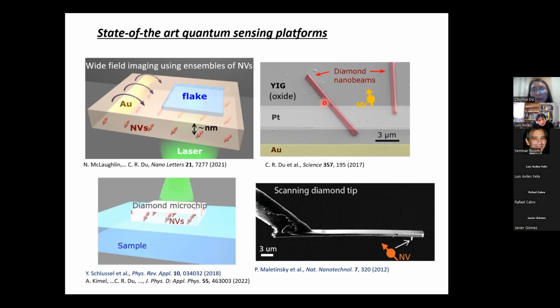So this includes patterning the diamond into diamond nanobeams with the width around micron size, or patterning the diamond into microstrips and transferring it on the material surface. So we can also use a fabricated diamond cantilever containing a single NV center at the end. Then we can attach this diamond cantilever to an atomic force microscope, so we can scan the tip on the material surface to achieve magnetic imaging. So for wide field imaging, the spatial resolution is about 500 nanometers, limited by the optical diffraction. And for scanning probe-based NV imaging, the spatial resolution is around tens of nanometers. So that's the best among other quantum sensing platforms.